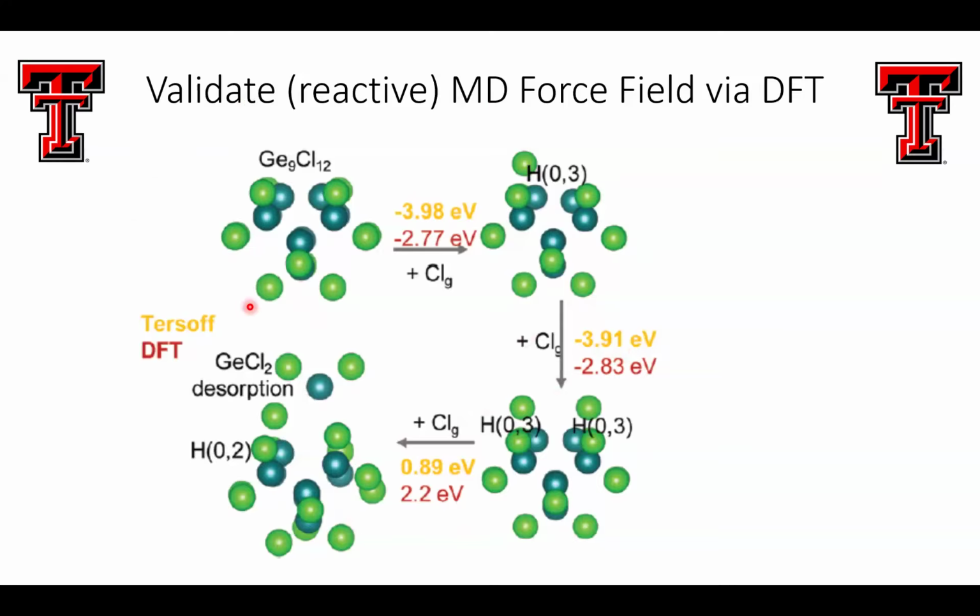So we calculated, using this reactive force field, these germanium chlorine clusters, calculated their energy, and did this both with density functional theory and with this Tersoff, which is this type of reactive MD force field. You see that the numbers are not the same. The main important part is the rank order of these energies has to be the same. Otherwise, you are getting the wrong physics.